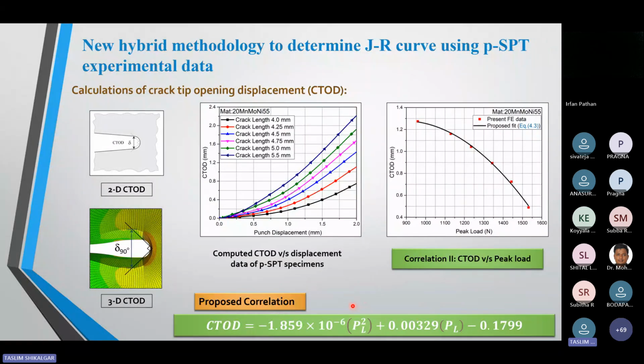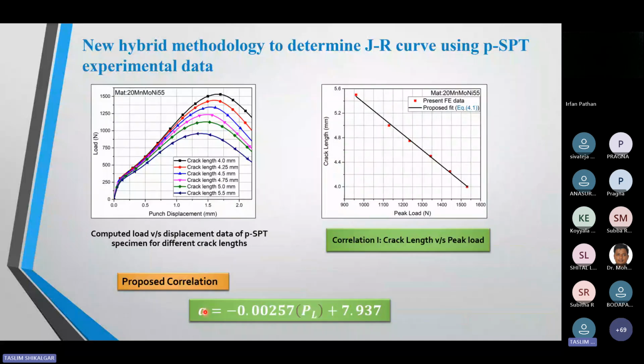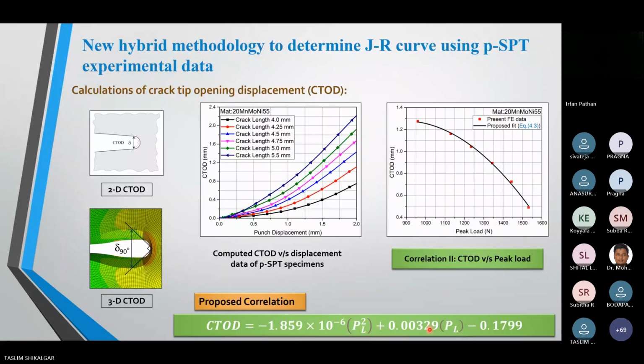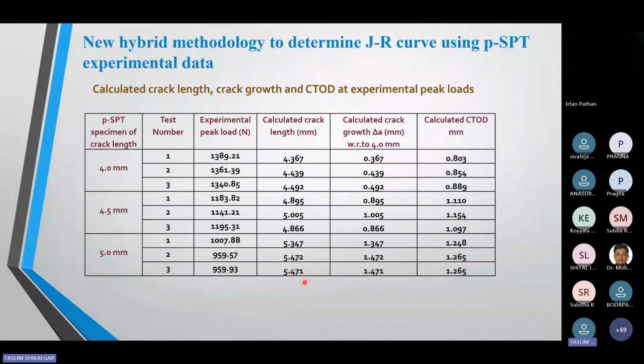Here I can get peak load data from the experimental data. I need to just put this peak load data in correlation one. So I will get the crack length, and from correlation 2, I will get the CTOD. So from these correlations, I calculated crack length, and these are the experimental peak loads for the 4 mm, 4.5 mm, and 5 mm specimens.